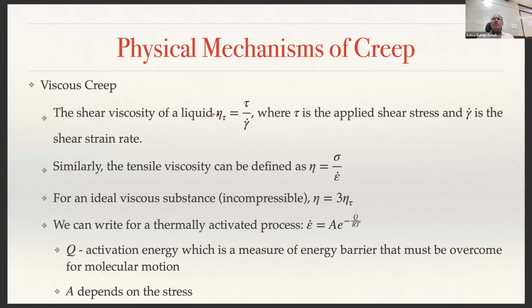So for the shear viscosity in fluid flow problems, you can write tau is equal to mu times gamma dot, where gamma dot is the strain rate. So here the shear stress by shear strain rate gives you the shear viscosity of the liquid, right? Similarly, you can also define something called tensile viscosity for a material as eta is equal to sigma by epsilon dot, where sigma is the stress and epsilon dot is the strain rate, right? And then eta gives you the viscosity. That is, if a solid material is creeping like a fluid, then this viscosity is what we call tensile viscosity, right? For an ideal viscous substance, which is incompressible, eta will become 3 times the shear viscosity of the liquid.